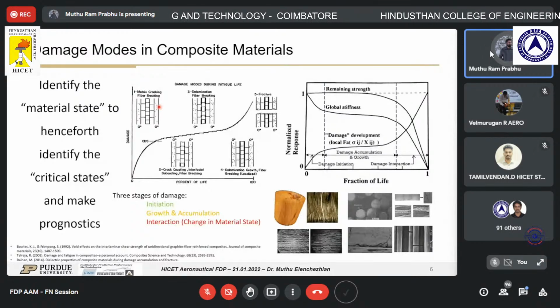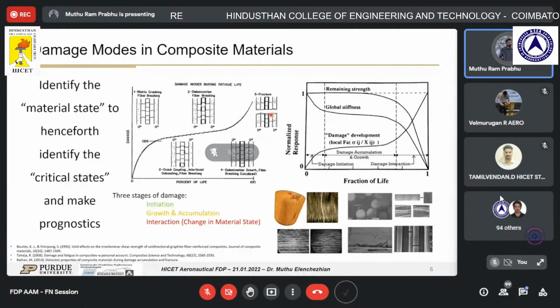First, in the initial stage, there's matrix cracking. So between the fiber and matrix, matrix cracking occurs first, and after that, over the duration of the life, the damage develops a lot, and the other 2 stages such as crack coupling and delamination will occur. And further, as it develops, the final fracture will occur at the final stage.